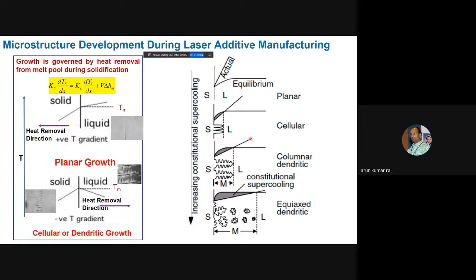Here you can see I have schematically shown how this happens. When the actual temperature in the liquid phase is much higher than the equilibrium temperature, you will end up having a planar interface. But if your liquid temperature is less than the melting temperature, just look at this region, then you can have this kind of protrusion formation. This is cellular structure formation. If you are interested in metallurgy, this kind of thing has been reported. Cellular structures have been observed in laser printed material.